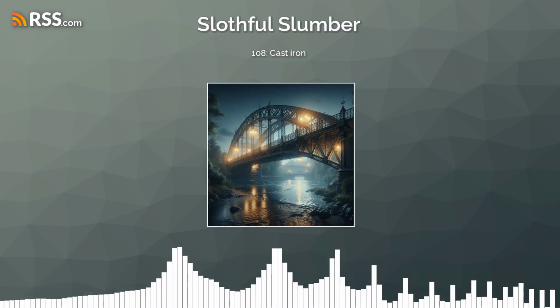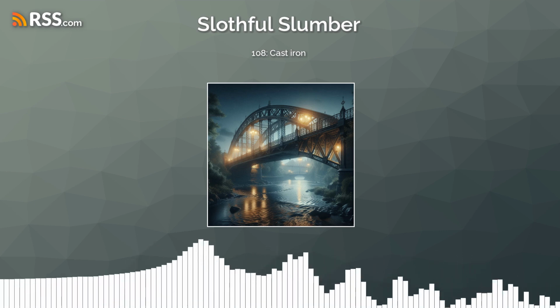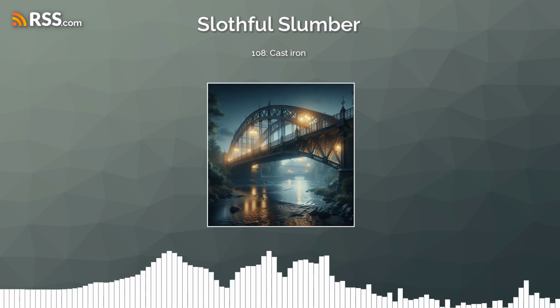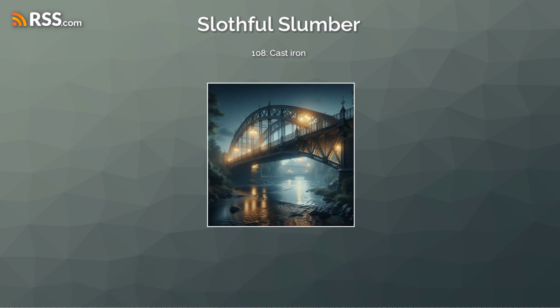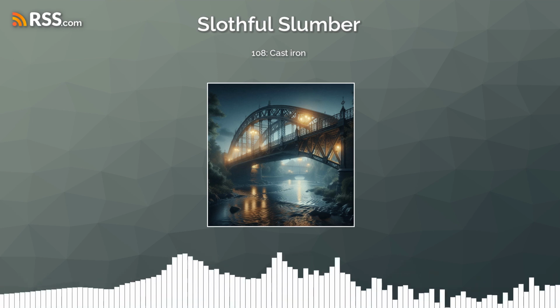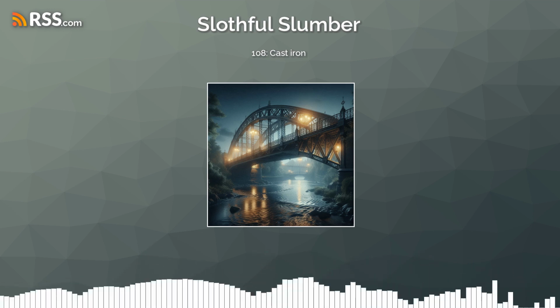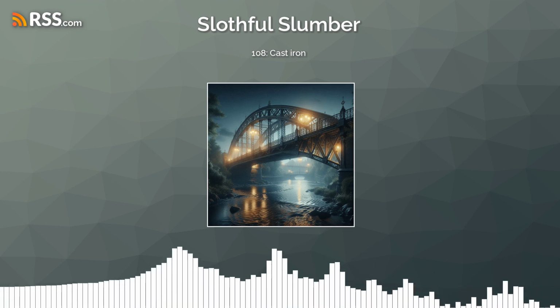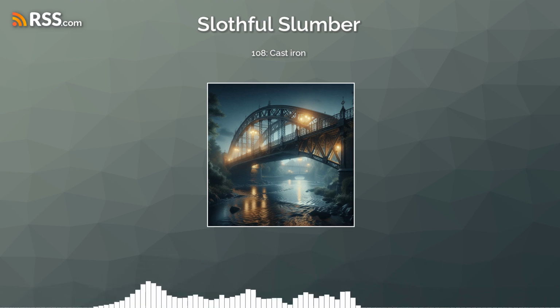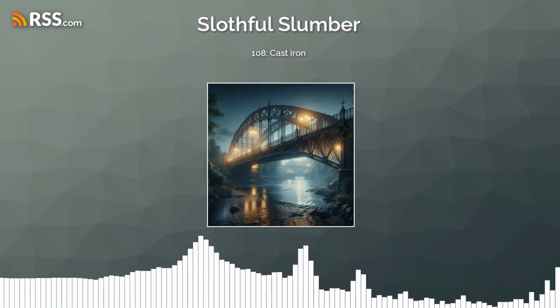As the iron carbide precipitates out, it withdraws carbon from the original melt, moving the mixture toward one that is closer to eutectic, and the remaining phase is the lower iron carbon austenite, which on cooling might transform to martensite. These eutectic carbides are much too large to provide the benefit of what is called precipitation hardening, as in some steels, where much smaller cementite precipitates might inhibit plastic deformation by impeding the movement of dislocations through the pure iron ferrite matrix.